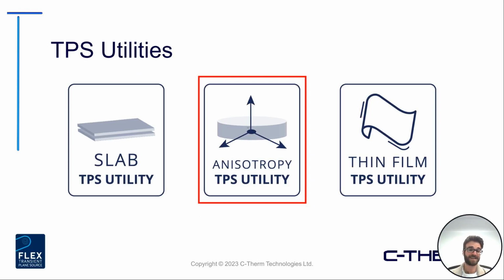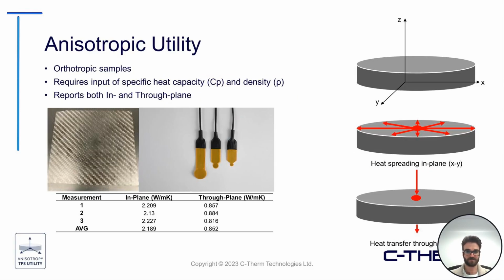The next utility we'll take a look at is the anisotropic utility. So, it's right in the name. It's for testing materials that are anisotropic in nature. Just wanted to highlight a little bit of a data set here. With the anisotropic utility, you do need to manually input the heat capacity and density of the materials that you're working with. This is required in the software because the software is doing some work behind the scenes. The anisotropic utility is well defined in the ISO if you want to learn more about how it works. But ultimately, what you get from the output of your measurement is both an in-plane and a through-plane thermal conductivity. So just an example set there. And again, if you're dealing with anisotropic materials, you're going to want to use a specialized mode for that to make sure you're collecting the most accurate data possible.